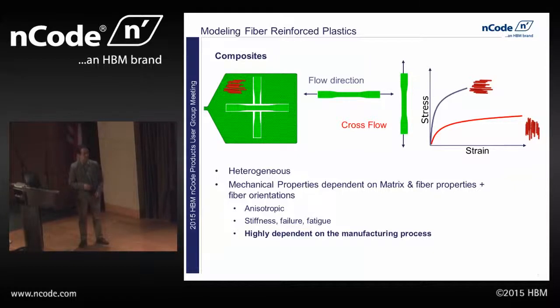You see this very nonlinear stress-strain curve. You see something that's very soft and very ductile when the fibers are not aligned in the direction of loading, and then something that's very stiff and very brittle when the fibers are aligned in the direction of loading. That's really the anisotropy showing itself. And this is true for both stiffness as well as failure, so you see these different strains of failure as well as fatigue. The whole point of all this is that these materials are highly dependent on the manufacturing process. Here I'm really talking about fiber-reinforced plastics, but the same could be said for any composite material that's anisotropic in nature, so continuous fiber composites as well.